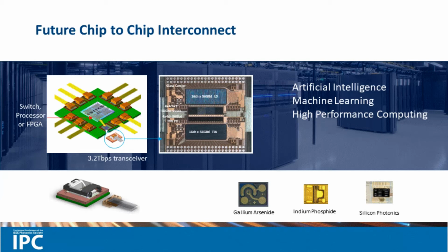Similarly, indium phosphide and silicon photonic integrated circuits are enabling multiple WDM wavelengths to be transmitted on individual single-mode fibers for chip-to-chip interconnection. With 16 wavelengths per fiber, and each wavelength operating at 25 gigabit per second over 8 parallel fibers, the upper left picture shows 3.2 terabit per second transceiver chiplets for switch-to-switch interconnection.